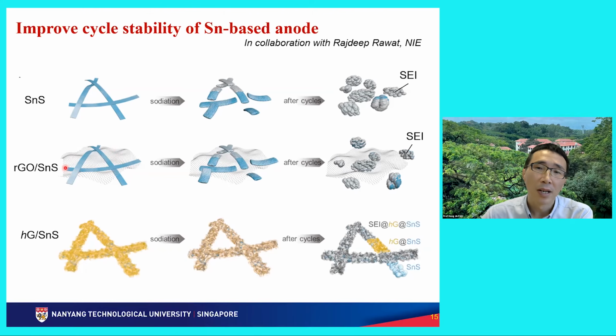And then you can do a physical mixture with a conductive carbon, which is reduced graphene oxide, a very popular material to enhance the conductivity and the stability of many metal sulfide materials. This, we also did. Still not good enough. Why? Because after many cycles, they still detach from the RGO. They also break into small pieces. And so the particle surfaces are still coated with SEI layers, very similar to the pure tin monosulfide.